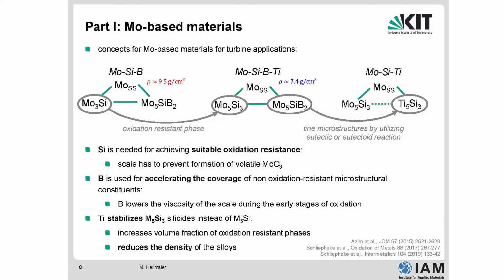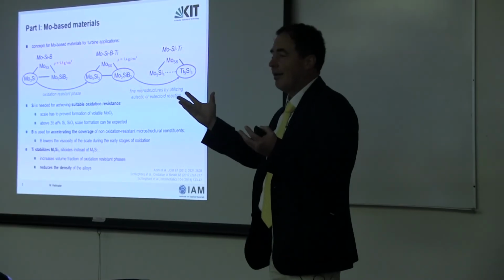Having just said that nickel-based alloys have a temperature limit of 1,200 degrees Celsius, roughly speaking, this is much higher. Now, a pure molybdenum-based material would not work in a high-temperature environment because of the following issue. You need suitable oxidation resistance. If you don't have chemical elements in the alloy which provide oxidation resistance, the alloy would oxidize rapidly. You would form, in particular in this case, a volatile molybdenum trioxide which just sublimates and goes away. So you form smoke of molybdenum oxide which rapidly evaporates.